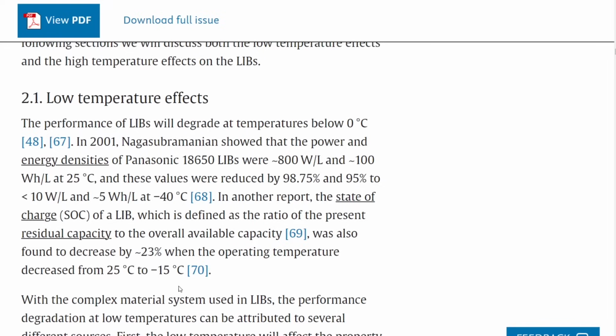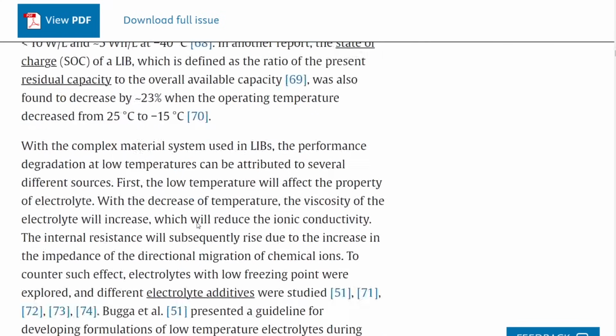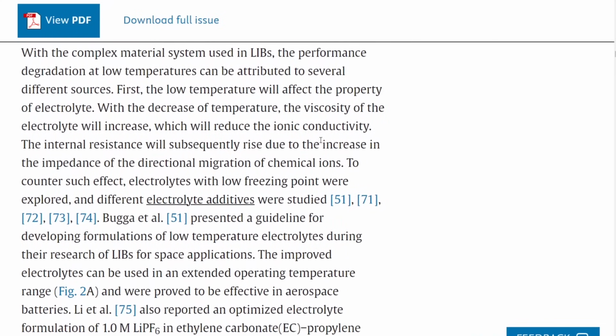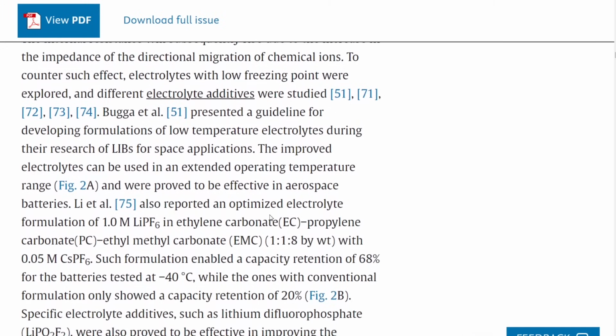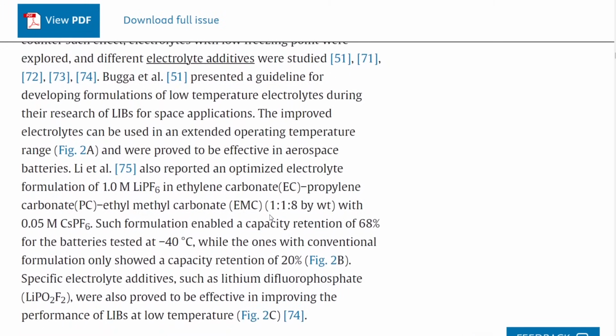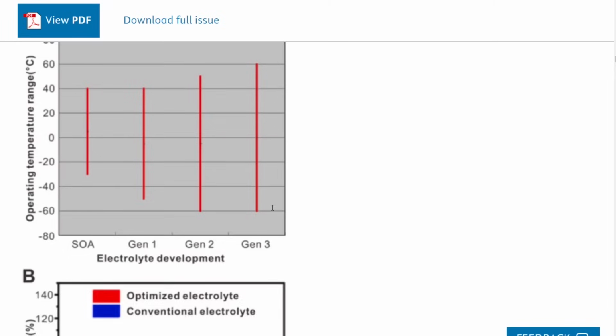When you drop temperatures to -15 degrees Celsius, which are temperatures fairly regularly reached in the colder parts of the world, in places where people live, they decrease capacity by as much as 23%. So a quarter, you lose a quarter of the capacity. And they talk about one of the major issues being the electrolyte, and you can change the electrolyte so they work better.